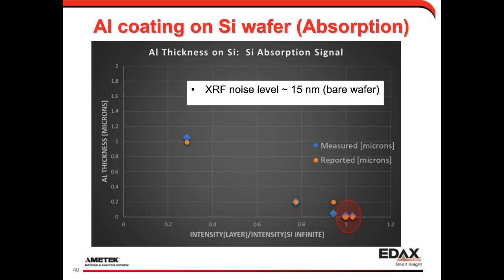To find the minimum limit, our standard deviation under these measuring conditions, where we're measuring for about 1 minute in this particular case, is about 10 to 15 nanometers. So our standard deviation is in that range of noise level. That gives us roughly an idea of what the minimum is. I'm thinking our minimum is around 40 nanometers or so, about 3 times the standard deviation. But it depends on how much precision you need in the measurement as to how long we have to measure for.